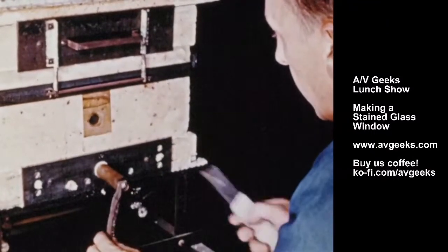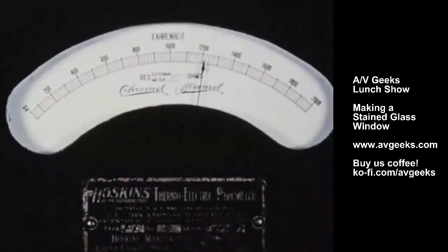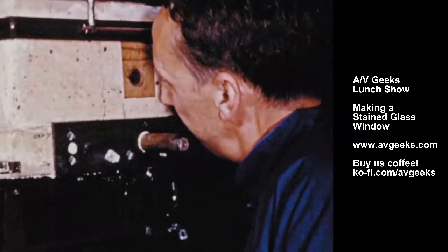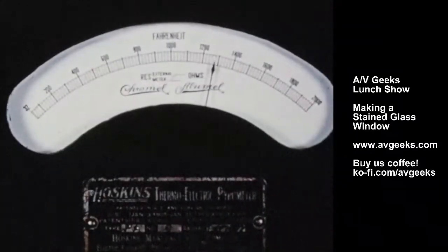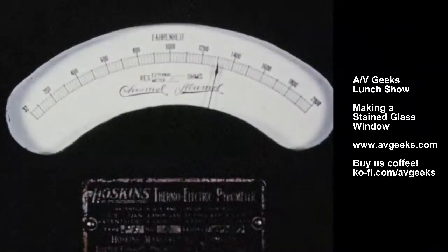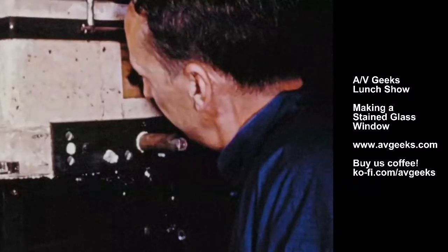Temperature alone will not accurately indicate when the glass has reached the firing point, which varies according to the type of glass and the ingredients in the paint. Experience and close observation are necessary at this critical stage. With the firing point actually reached, the glass is practically at surface melting heat. Firing continues a few minutes until paint and glass are firmly fused together. Here again, experience is needed to determine when the glass has received just the right amount of firing.